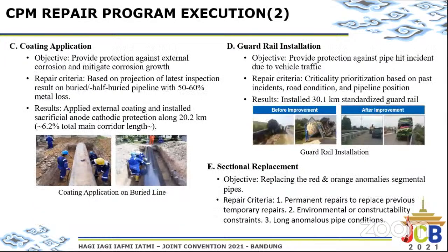The third program is coating application. The objective of coating is to provide protection against external corrosion and mitigate corrosion growth. The repair criteria is based on the projection of inspection results on buried or half-buried pipeline with 50 until 60% metal loss. Total coating application and sacrificial anode installed until 2020 is around 20 kilometers, equal to 6.2% of the total main corridor length.